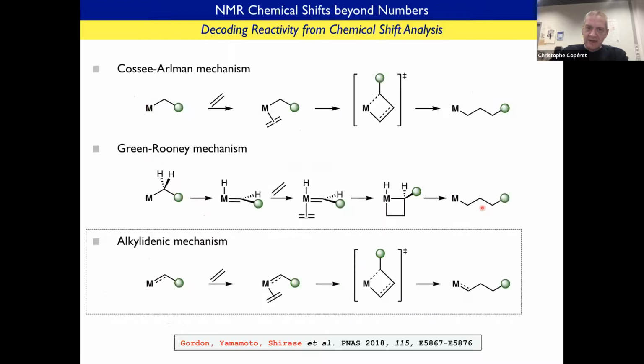So typically, when you taught organometallic chemistry before our work, you would always discriminate two types of mechanism, and people would always say that olefin polymerization has to take place via this mechanism and not via this one that implies the formation of a metal alkylidene. What we have shown in our work using NMR spectroscopy is that the truth is in between the two mechanisms that were proposed for basically 30 years, and that you actually need this pi bond character to enable a chemical reactivity and olefin polymerization.